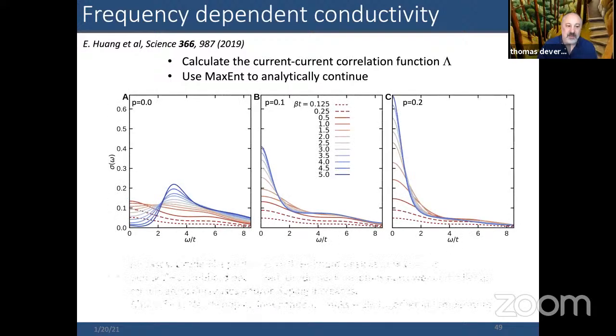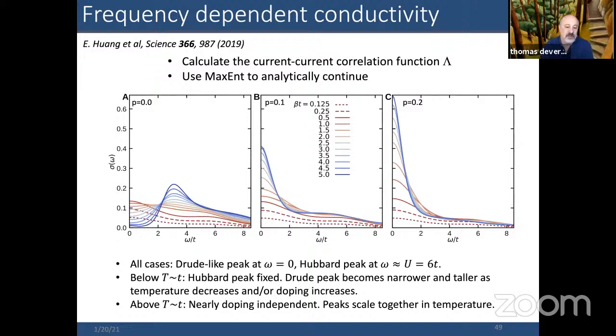So here are plots of sigma of omega versus frequency for three different values of doping: half filling on the left-hand side, 10% in the middle, 20% on the right. For hot temperatures, which are the dashed or dotted lines, down to cold temperatures as far as we can get, which is the solid blue line. So on the left-hand side, you can see you have a gap as you go to low temperatures, meaning the spectral weight depletes at low energies, and it piles up at the absorption peak, which is a little bit below the Hubbard peak, which should be at 6t for these simulations. So indicative of it being an insulator.